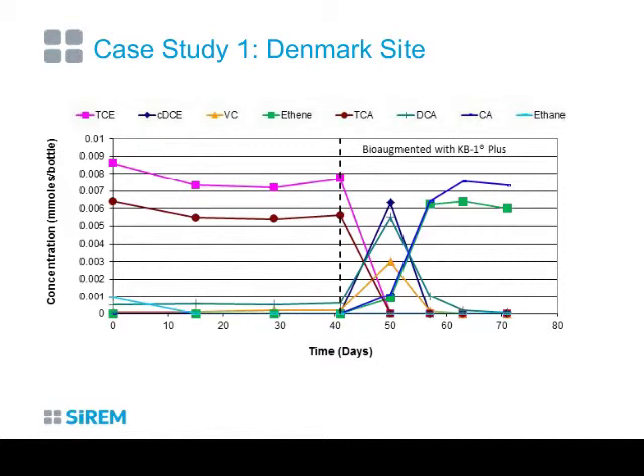And you can see fairly nice mass balance with the amount of TCE that we started off with. And then the TCA degrading from the red into 1,1-DCA, which is the turquoise underneath here, and then going to chloroethane. Chloroethane is not further degraded under anaerobic conditions, but then can be degraded under aerobic conditions.